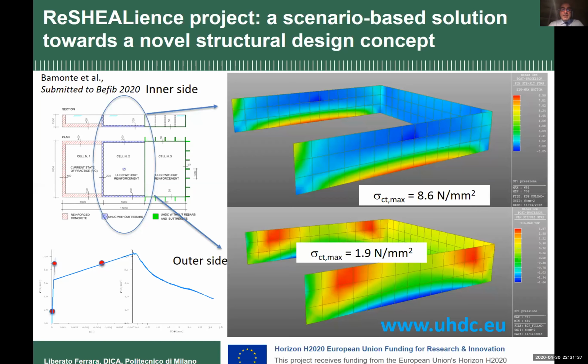But you can see that 9 megapascals is still within the strain hardening behavior regime of this material. It's a regime where you form multiple cracks, each one very, very narrow, very tiny open. So in this case, there are no problems in withstanding this level of stress.